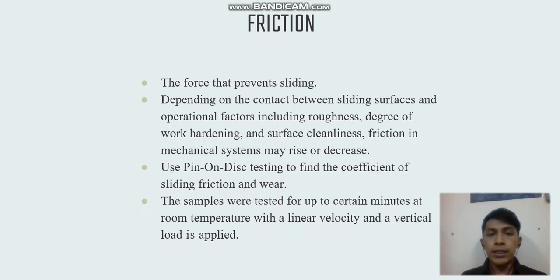For the other tribology, it is friction. Friction, also known as the force that prevents sliding, depends on the contact between sliding surfaces and operational factors including roughness, degree of work hardening, and surface cleanliness. Friction in a mechanical system may rise or decrease. I will also use pin-on-disc testing to find the coefficient of sliding friction and wear. Then the samples were tested for a certain number of minutes at room temperature, with a linear velocity and vertical load applied.